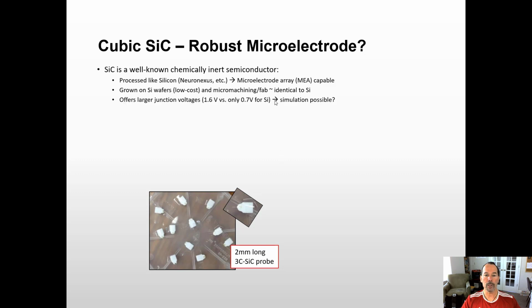So one interesting thing that we can think about is we can use PN junction isolation, where we alternate hole-rich and electron-rich materials. In silicon, we have a very low turn-on voltage of 0.7 of a volt. Great for electronics, not really good for stimulation with a p-n junction diode on a probe. But with silicon carbide, we have a little bit more than double the turn-on voltage. So now you can imagine doing stimulation up to a volt without having to worry about leakage current in the p-n junction. And I'll talk about that a little bit later.